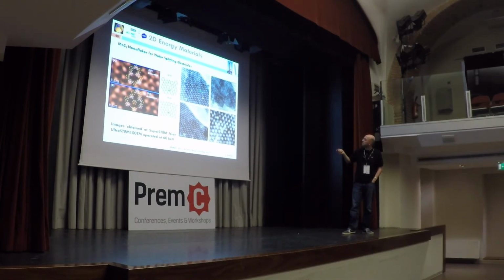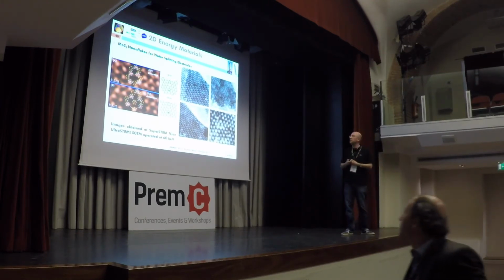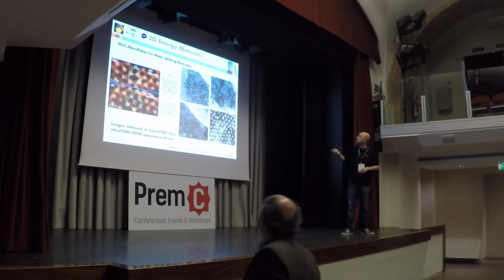And you can see here, what we wanted to know is, this is a grain boundary, and we wanted to know exactly what was the atomic distribution at the grain boundary, because then by DFT, I will not show it here because it's not published, but by DFT, you can calculate the efficiency of these grain boundaries and these defects towards the evolution reaction of hydrogen or oxygen.